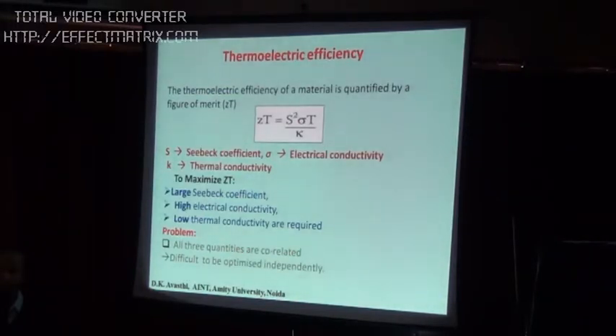The thermoelectric efficiency can be quantified by this factor, ZT, which is S squared sigma T by K. S is the Seebeck coefficient, sigma is the electrical conductivity, and K is the thermal conductivity. It is very clear that if I want to maximize ZT, then I should have a large Seebeck coefficient, high electrical conductivity, and low thermal conductivity. But there are problems because these three things are actually interconnected. So what should be the strategy?